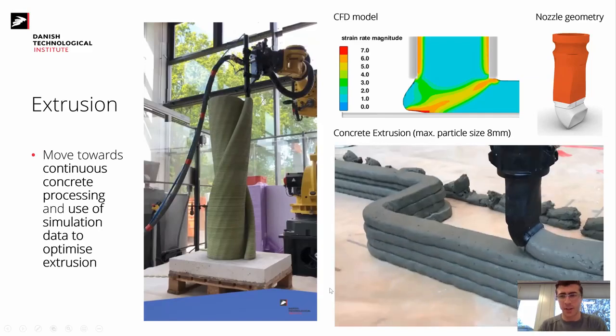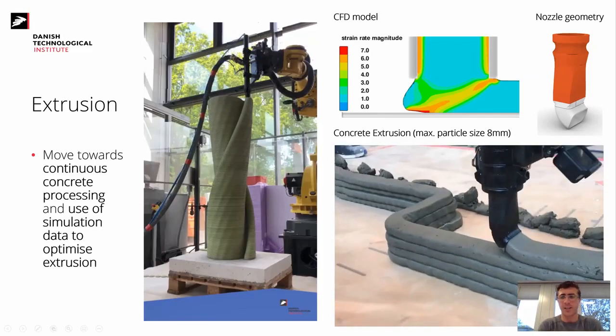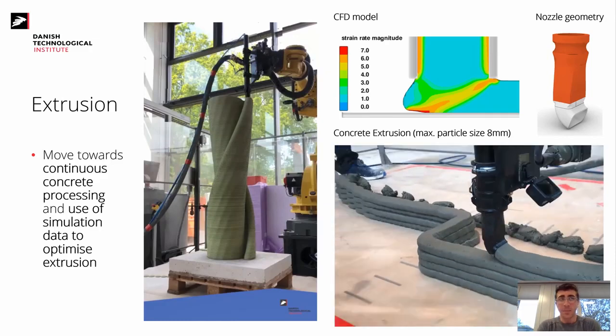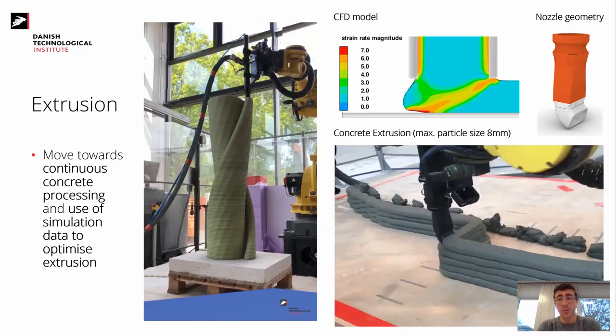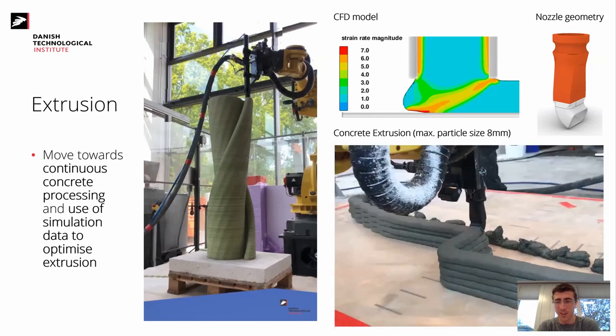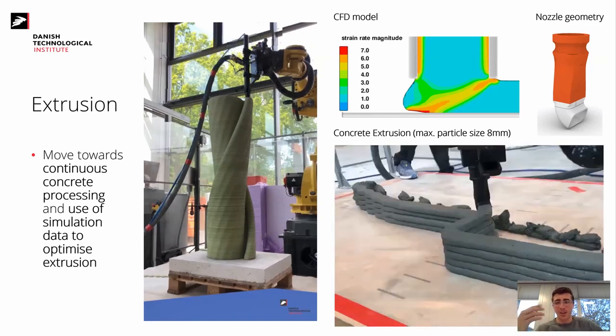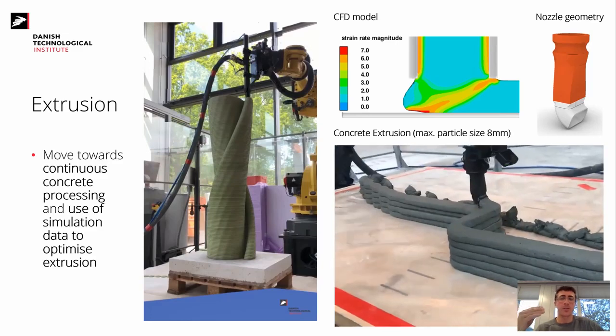And this mix here that I'm showing last in the video at the right-hand side, it's a mix that has up to 1,500 kilos per cubic meter of aggregates. I'm sorry, the video is a little jerky there, but it has up to 1,500 kilos per cubic meter of aggregates, with about 56% of that being aggregates up to 8 millimeters.